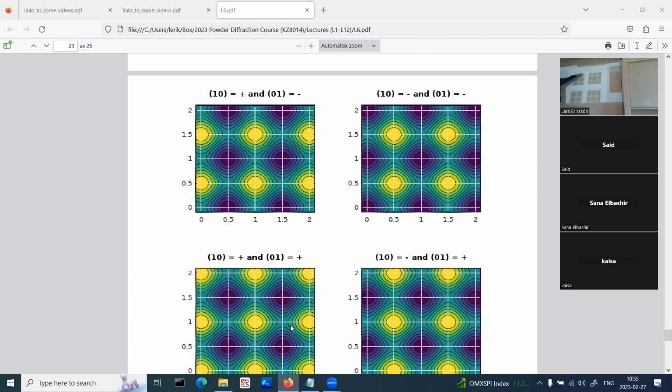And when the phase is negative, -1, in the 0 1 direction, that is the Y direction, or the K direction maybe in reciprocal space, there is no density in the origin, but halfway through. And minus stands for a phase equal to pi, and plus stands for a phase equal to 0, or possibly 2 pi.